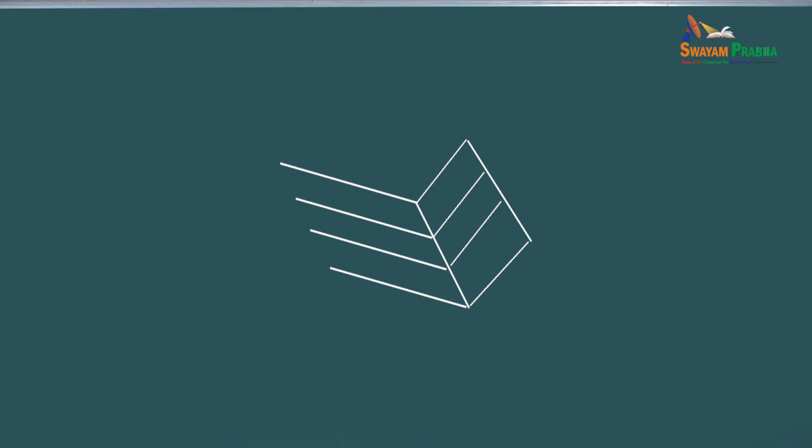And for the dislocation to be common, the Burgers vector has to be parallel to the intersection. So in our case here, that would be an AB dislocation. You see what I mean? So I have an AB dislocation, which is on this plane, and then it can also be on that plane because the Burgers vector is common to both planes.